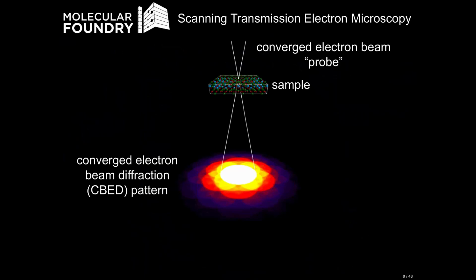And so this pattern is extremely rich in information. It contains all the crystallography and scattering information in the sample. It has information about the thermal vibrations, the phonon spectra of the sample. There's also energy losses here. You could do electron energy loss spectroscopy, for example, EELS, to measure those energy losses and do spectroscopy on the core states of the sample or the low loss states.